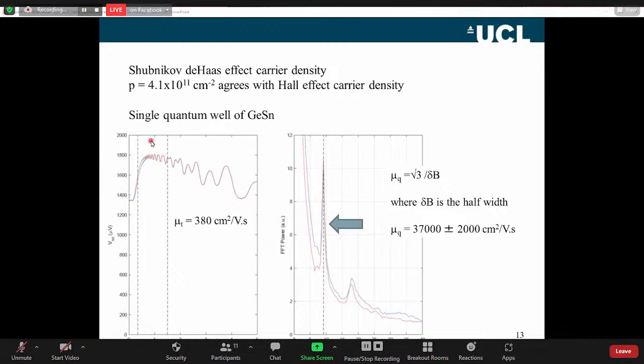If we Fourier transform these oscillations, they are periodic in 1/B, and we get out something called the fundamental field. That fundamental field is related to carrier density. Interestingly enough, this is a Fourier transform of the data between the two lines here. The peak in the Fourier transform is related to quantum mobility, 37,000. As I said earlier, it's characteristic of a material that might have a transport mobility of 1 million. But in this material, the transport mobility is only 380. Very, very unusual system.